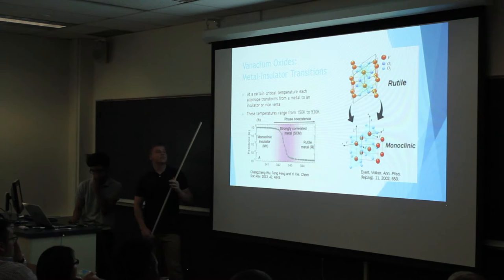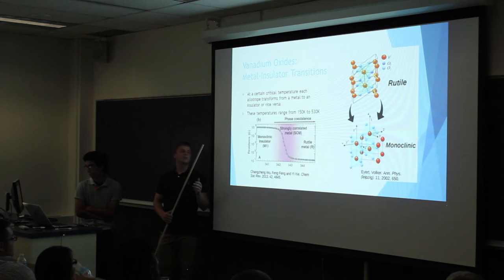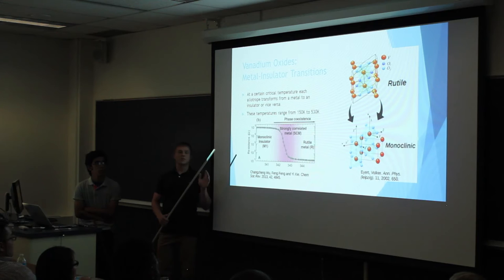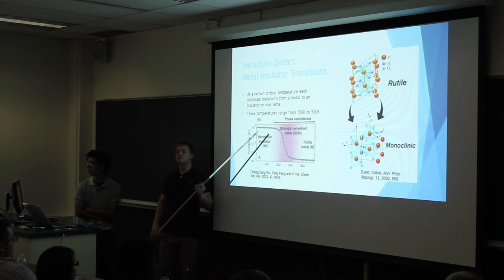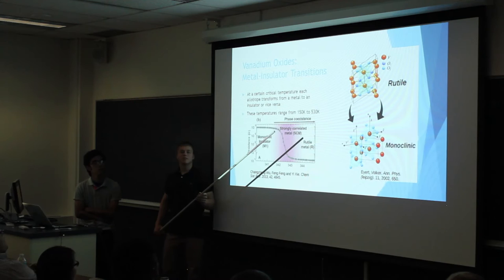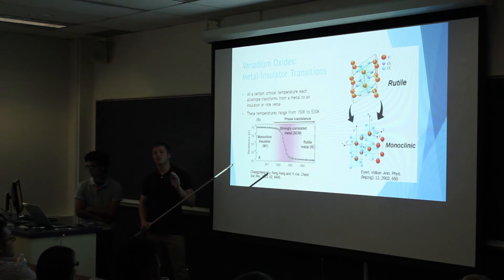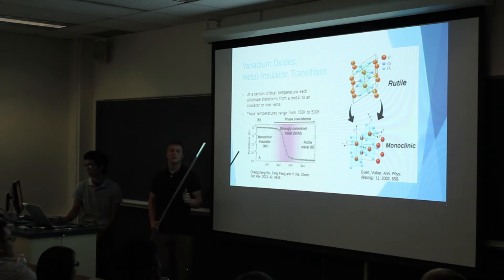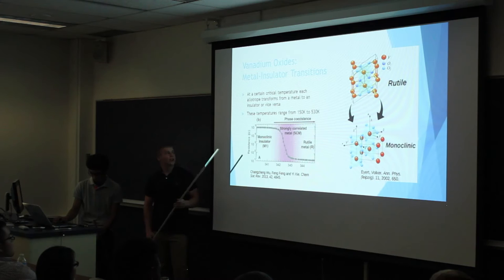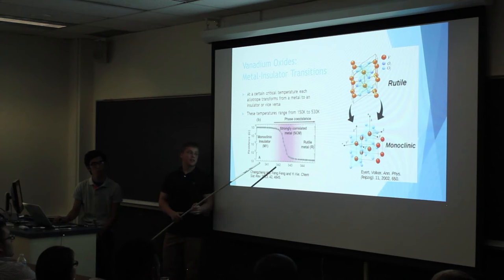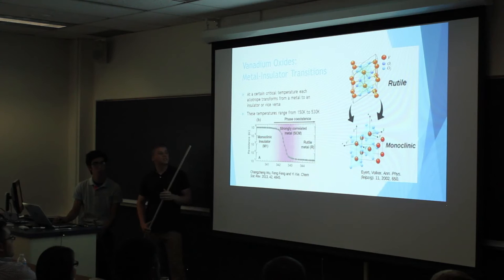To talk about the metal-insulator transitions themselves: at a certain temperature called the critical temperature, each allotrope transforms from a metallic phase into an insulating phase or vice versa. Depending on each allotrope, the temperatures can range — for the ones I'm focusing on, it'll be between 150 kelvins and 530 kelvins. Vanadium dioxide starts off in the high-temperature metallic rutile phase, then transforms into the low-temperature monoclinic insulating phase. It's this change in structure that causes changes in electronic and optical properties.